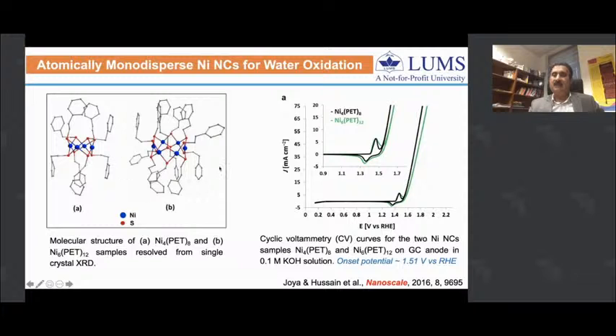And single crystal XRD. If you're able to crystallize these nanoclusters, you can characterize them by single crystal XRD. In this way, we found that they have either 4 or 6 nickel atoms, and interestingly, they were able to reduce the thermodynamic and kinetic barriers for splitting water.